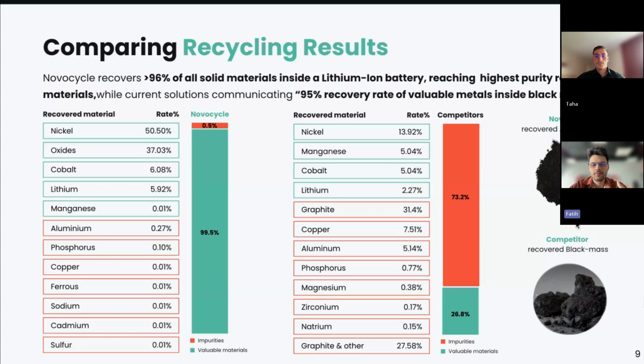So in total, we can summarize that with the technology that we are providing to this day, at Novocycle we can recover more than 96% of the solid materials with a high purity, so above 99%, compared to the right side, which was also shown previously, where the valuable material composition within the black mass is only maximum about 27%, and this needs then to be run through a chemical process to really get rid of further impurities. The organic compounds are not listed here. Usually the binders or the electrolytes are still present in the black mass, and they definitely need to be extracted. So there's a lot of post-processing required if we go to shredding and black mass. However, if we do this dismantling route that we're proposing, we can really directly reuse the material as it's extracted from the electrodes. So we can go to the next slide.